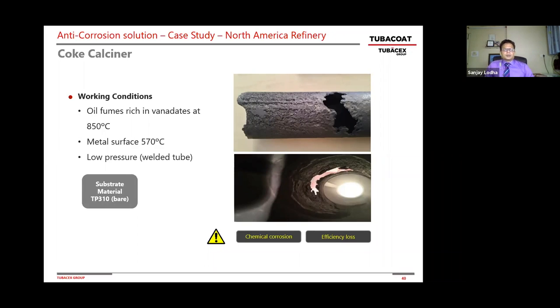Okay, as you can see on the screens, the flue gases in this recuperator heater in the coker calciner are extremely corrosive. You have sulfur, you have vanadium, and you have a very corrosive environment. The metal surface is at 570 degrees Celsius, close to 1000 degrees Fahrenheit. The tubes basically can't survive this environment, and that causes chemical corrosion due to the vanadium and sulfur. They have to plug the tubes, and that's a huge efficiency loss and operating cost, and then they have to reduce the throughput in the coker calciner.